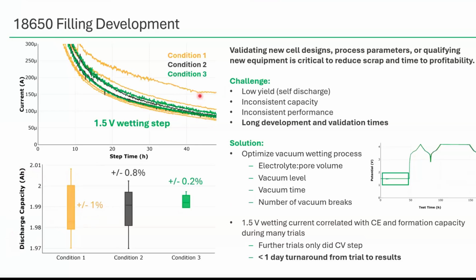We were able to do that with very precise current measurements in just a couple hours, within a day moving on to the next set of conditions without having to put those cells on test to wait for those measurements. Once we confirmed we could really do high throughput experiments in just a day, we honed in on using UHPC during this formation step to get to our optimal conditions faster.